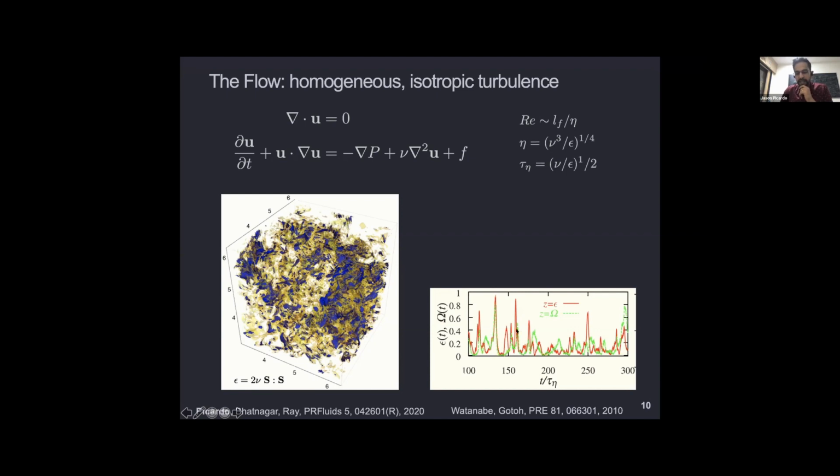So a better time scale is actually the inverse Lyapunov exponent. Lambda is the Lyapunov exponent, and it goes as about 0.151 over tau eta for our simulation. Because this basically characterizes the exponential separation of 2 points in the fluid that start out close together at long times. So it's really an appropriate quantity for polymer stretching, and this has been studied in detail in past work.